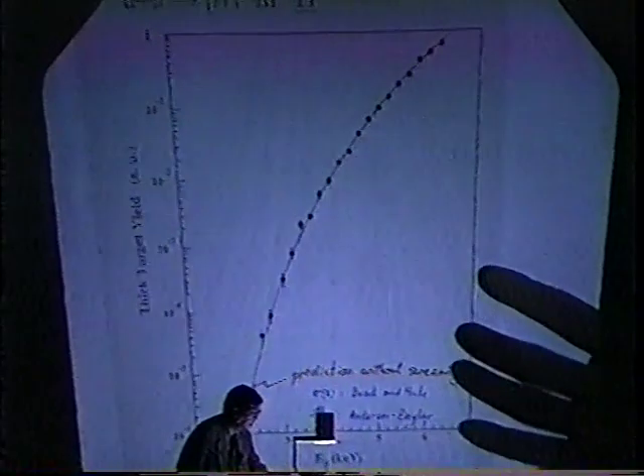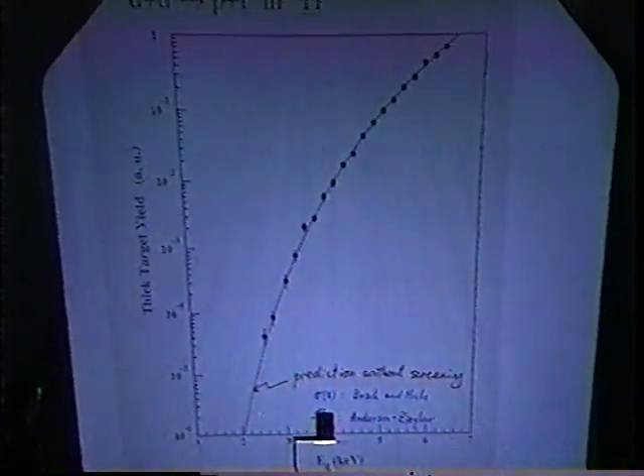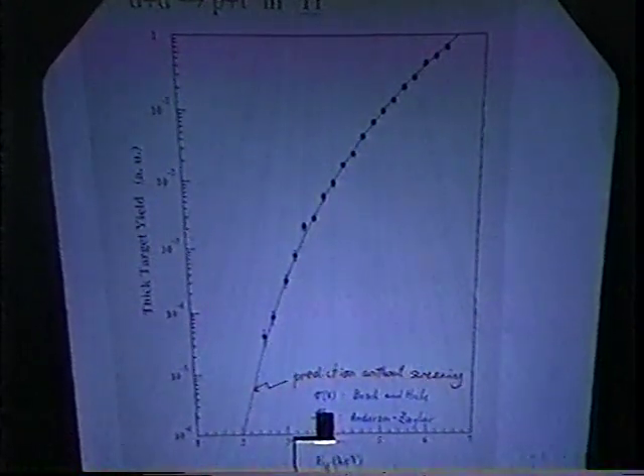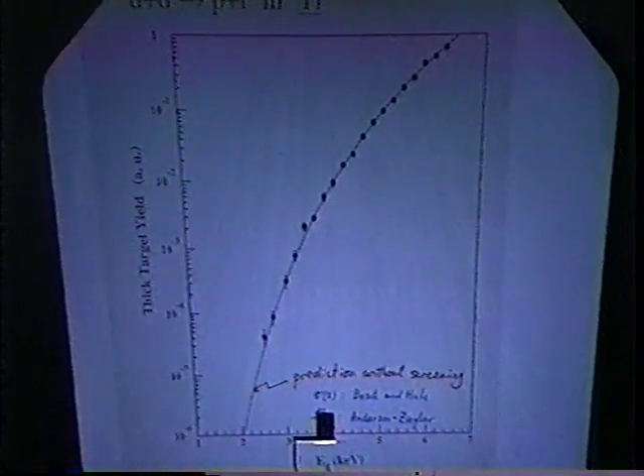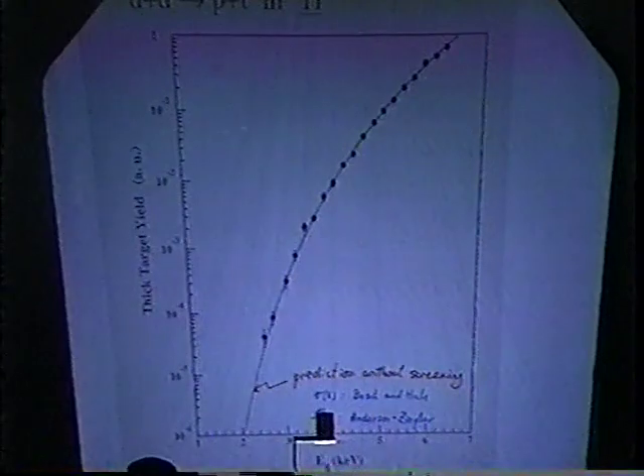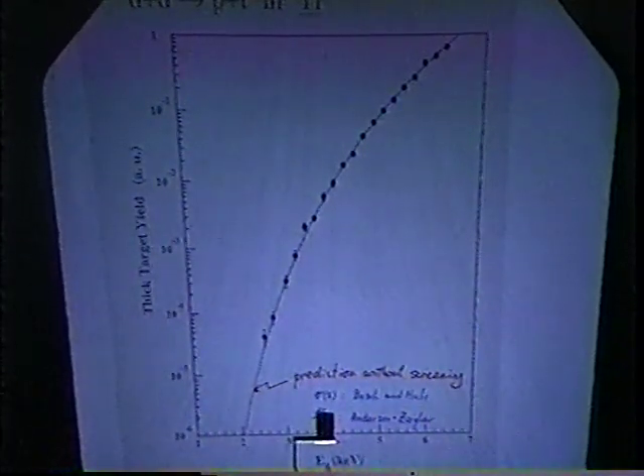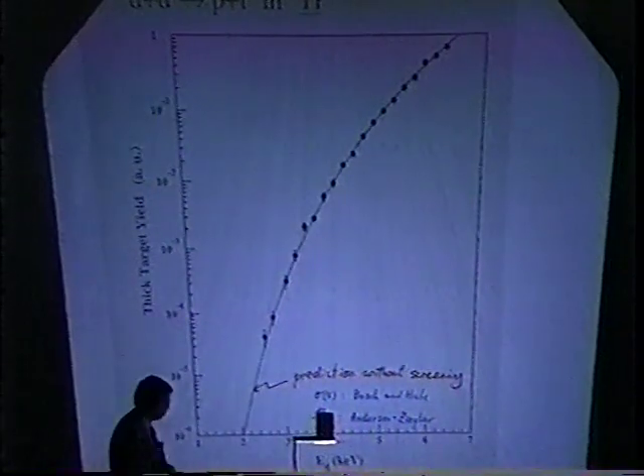So here the result for the titanium case. And as you see, the reaction rate decreases very quickly. Only the, let's see, 1, 2, 3 keV difference makes 1, 2, 3, 4 order of magnitude difference. And then this is the prediction without the screening, to predict these reaction rate.